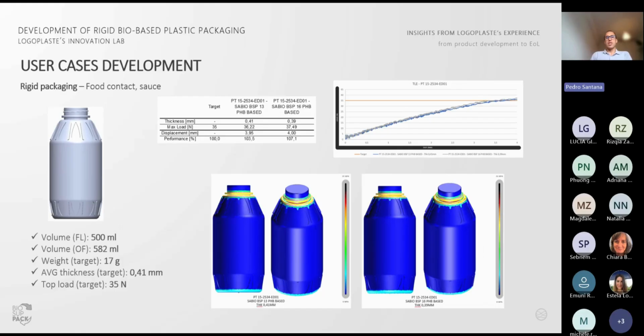And finally, the sauce packaging case study presented a particularly interesting result because although it had a less demanding top load specification, the average wall thickness obtained was once again similar to the ones before. This outcome is mainly due to the bottle's geometry and design, especially in the neck area where there is an almost horizontal section here. You can see here, with a relatively tight angle. This configuration causes stress concentration, leading to a failure mode under relatively low loads, even when the wall thickness is adequate. Here, you can see that small details of design can lead to very underperforming packaging.